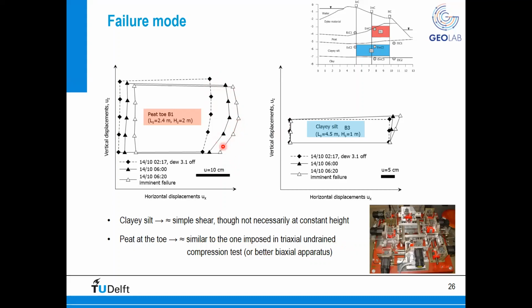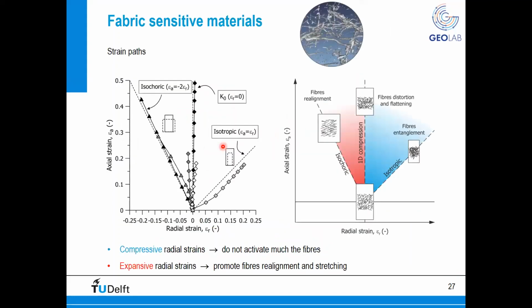And having the knowledge of the failure mode of this material, in my opinion, is extremely important, because peat especially is a fabric sensitive material. So we often speak about stress path, but for this material, which contains a lot of fibers, in my opinion, it's more appropriate to speak about strain path.